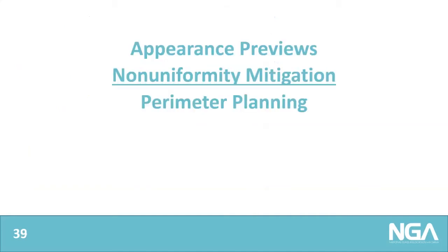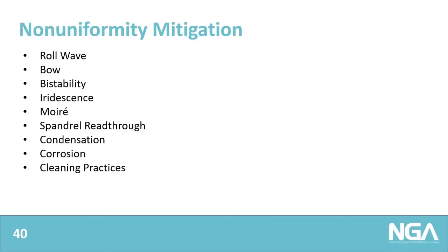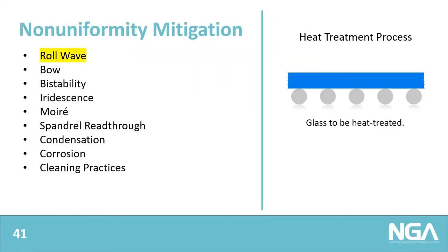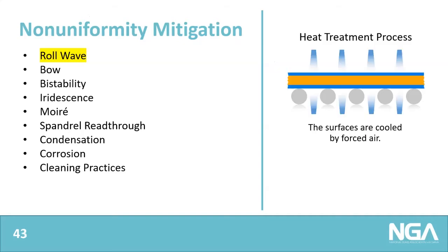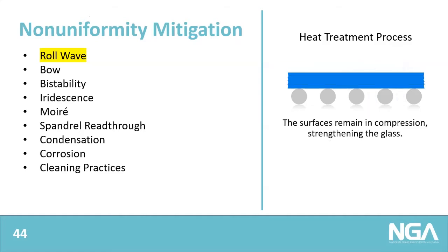Okay, let's move to non-uniformity mitigation, beginning with roll wave. And to talk about roll wave, we really need to introduce the heat treatment process. So in a nutshell, the way it works is we have glass that is to be heat treated. That glass is heated, and then the surfaces are cooled by forced air. And this causes the surfaces to remain in compression, which has the effect of strengthening the glass.